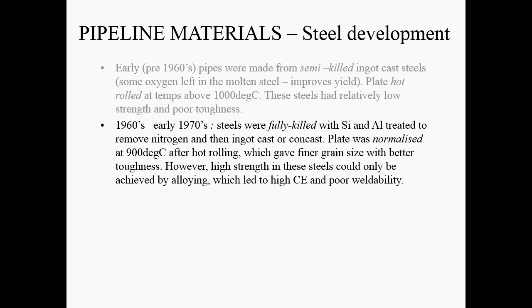So the only way you could actually increase the strength of the steels is to add alloying elements, chromium, nickel, vanadium, that sort of thing. Now that's great, puts the cost of the steel up, not so great, and makes it more difficult to weld, definitely not so great if you're going to make a pipeline. So all alloying elements that were added to steel at that particular time increased the carbon equivalent. CE here is carbon equivalent, and again we'll talk about that a bit more fully later on. But the more carbon there is in a steel, the more difficult it is to weld. So if alloying elements are equivalent to adding carbon, the steel's going to be more difficult to weld.